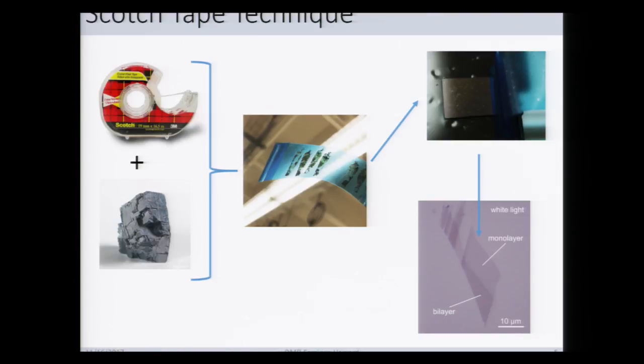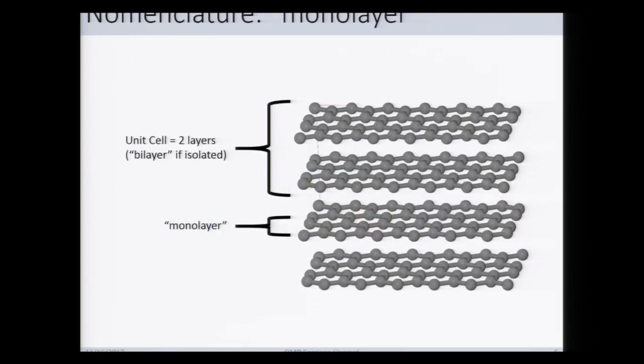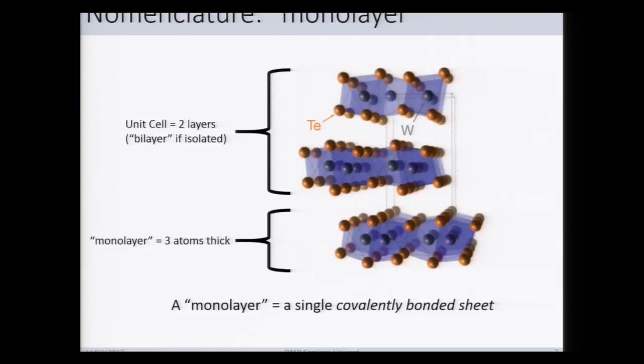When you look a little bit closer, you see actually these are little 2D crystallites of, say, in this case, monolayer graphene. And as a bit of nomenclature, for those of you not familiar with the field, what does a monolayer mean? Well, in the case of graphene, it's pretty simple. You have a single atomic sheet of carbon, which is actually less than the unit cell. So we see that this has nothing to do necessarily with the unit cell of the three-dimensional parent compound. And this gets slightly more complicated in other systems that are not graphene or boron nitride based, where, say, in tungsten ditelluride, which this represents, we have a 3-atom thick monolayer. So you have a tungsten atom sheet at the center and tellurium atoms on either side. So this single covalently bonded sheet is what we call the monolayer that is the thinnest limit that we can get to with the Scotch tape technique.